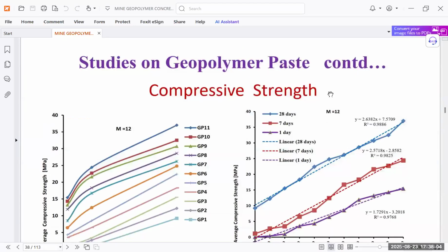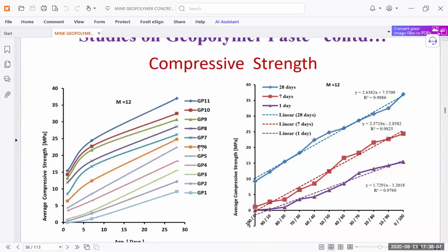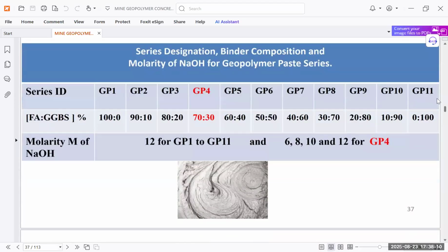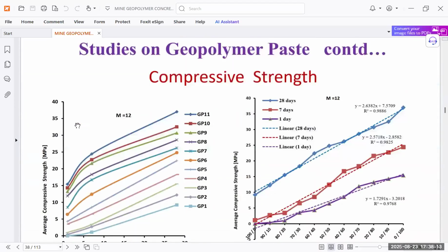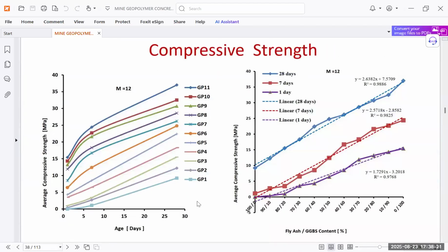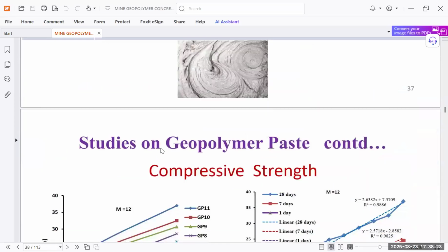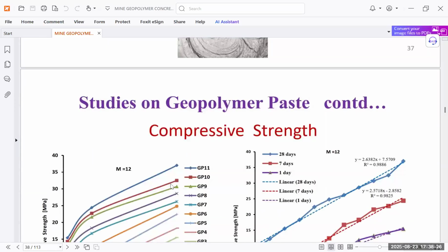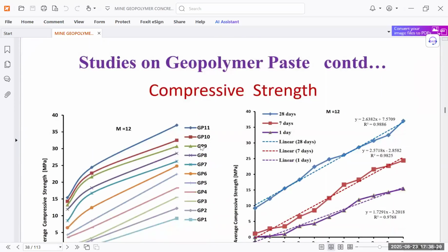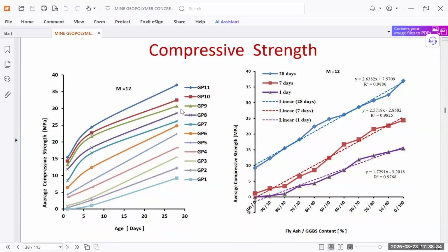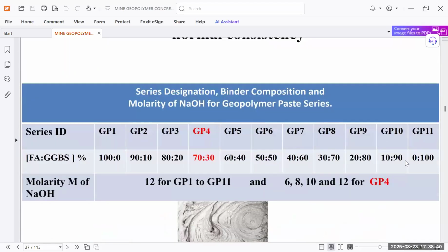So studies on geopolymer concrete paste have been done. You can see these graphs have been plotted for the different geopolymer concretes GP1 to GP11. You can see the compressive strength. This is for molarity 12, this is also for molarity 12, and this is also molarity 12. You can see it as per the age, and these different colors show GP1 to GP11. You can see blue is for GP11 and GP10 is for this. For GP10, you can see the average compressive strength at different ages is something like this. For GP10 we have used a 10 to 90 ratio: fly ash is 10% and GGBS is 90%.